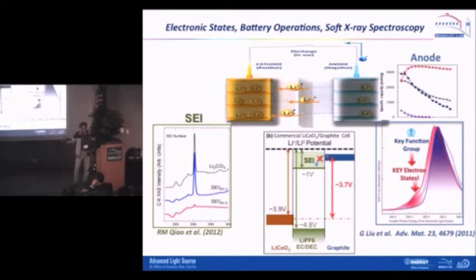And this tells you a little direction on what is the next step, what is the chemical species you are shooting for to form this SEI, and also you need to pay attention to the electrode itself. Although the SEI is normally considered just the reduction of the electrolyte, it's clearly affected by the electrode too.